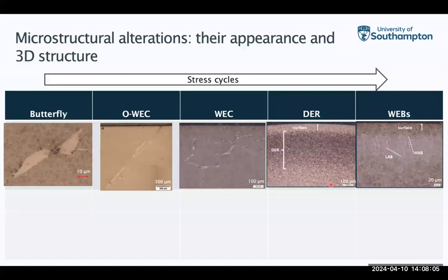So if you compare the appearance of these structures, I deliberately put them from left to right as increasing cycles, so the appearance in the life of the bearing. I have to clarify that the sequence of occurrence between butterfly, orientated white etching cracks and white etching cracks is not 100% clear. It's not that butterfly will definitely appear earlier than orientated white etching cracks and white etching cracks, but they're probably similar. They all appear in a very early stage of bearing lives, but they are all earlier than dark etching region and white etching bands, while the low angle bands occur earlier than the high angle bands.